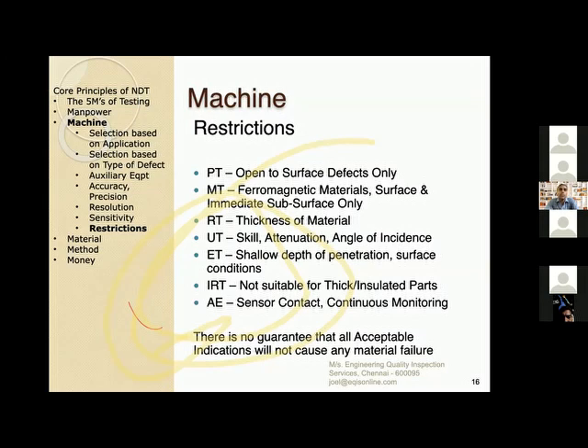And if I'm using an acoustic emission sensor device, then it requires 24 hours monitoring. I need to make sure that the sensor is always in contact. If I put a duct tape and it has loosened itself from the surface, then it will look like everything is normal, but actually there would be a crack that is being missed out. So all these are practical difficulties we usually face with the choice of equipment, and each technique has its own limitations.